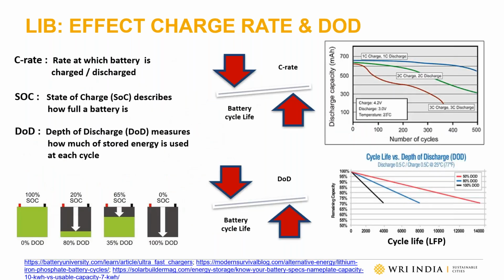In this slide, I have summarized how C rate, SOC, and DOD can influence the battery performance. We often discuss that this particular lithium-ion variant can be used for high charge discharge rate. But one needs to understand how the choice of charging and discharging can influence the battery life or cycle life of the battery. C rate is the rate at which the battery is charged or discharged. With a high discharge rate, the battery cycle life decreases.